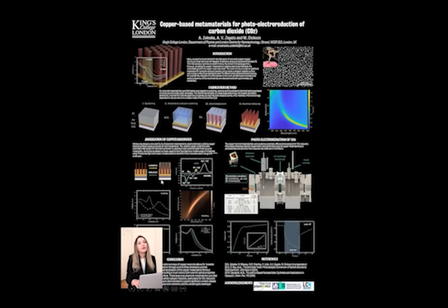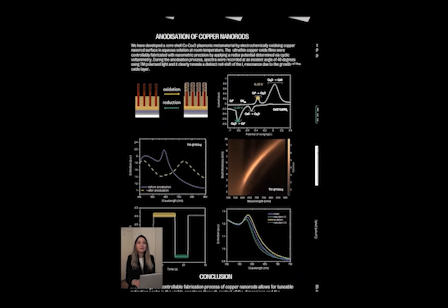Copper nanomaterials are often at a disadvantage when compared to noble metals because of their potential for oxidation. Reframing this problem and instead harnessing the photocatalytic properties of copper oxide, we created core shell copper oxide metamaterial by controllably growing copper oxide layers with a nanometric thickness using the technique of anodization. This process can be monitored optically in real time using UV-visible light spectroscopy.